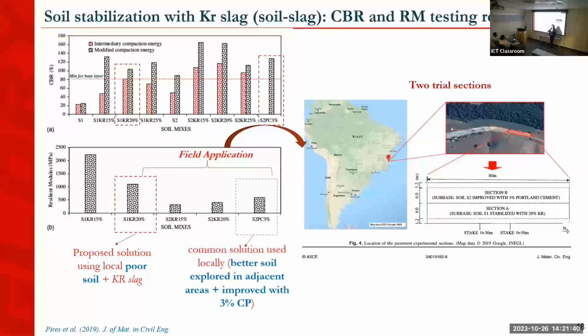But our alternative was, instead of using a soil that is not available close, where you have to go a little bit far to get this better quality soil and you have to mix it with 3% of cement, why don't we use this poor soil but mix it with slag? Because we saw some similar mechanical performance. So we selected those two soils and we built field sections.